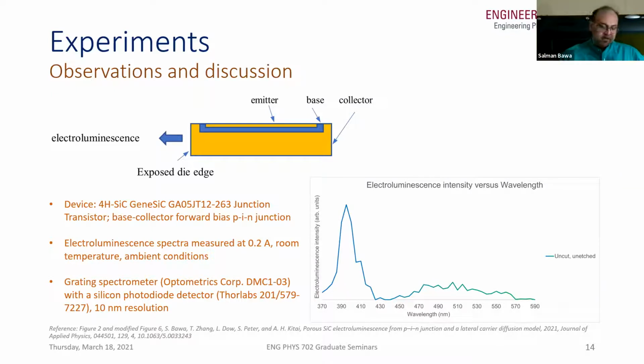So the narrow blue peak is a very well-known peak light emission that we get from silicon carbide band-to-band recombination. The broad green spectrum is also known and attributed to defects in silicon carbide. And our hope was that if we are able to somehow increase the defects in silicon carbide, would we be able to encourage the electrons and the holes to then transport to these defect centers and recombine there rather than recombining in the blue region? So that is what we are trying to achieve.